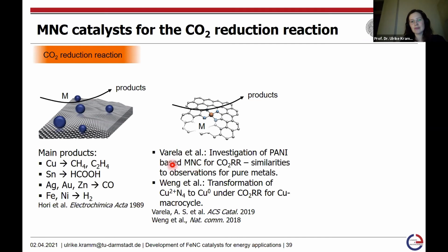They were able to see quite similar trends in comparison to Hori, but when you have a closer look at their preparation and also compare it to other works where you find structural characterization of this type of catalyst, then you can see that there are a lot of impurity species present within this catalyst. So based on that, the question is whether it is indeed the metal-N4 centers which give a similar trend, or whether these are the impurity species that give the same trend as in Hori, because it is basically the same species as investigated by Hori.